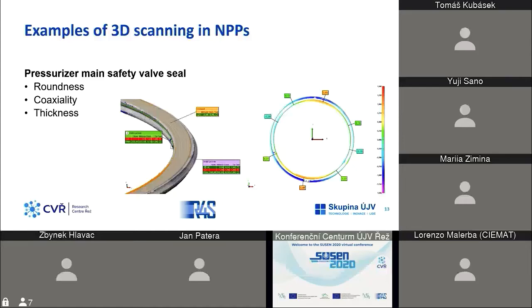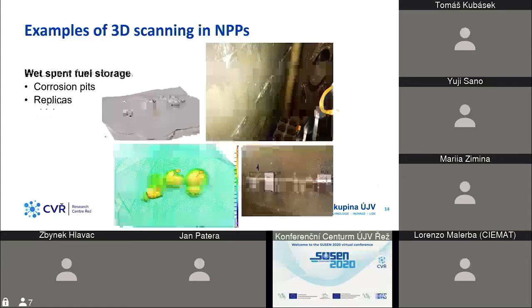In this application, we had to measure the pressurizer main safety valve seal. In fact, it was 24 newly delivered pieces where we measured roundness, coaxiality, and thickness, and everything was automatically assessed. And a very specific application was scanning of corrosion pits in wet spent fuel storage in Řež. Because of the poor access, we first made some replicas of corrosion pits, and then we scanned them. And the assessment was much more accurate from a point of view than the previous one that was done by microscopes.